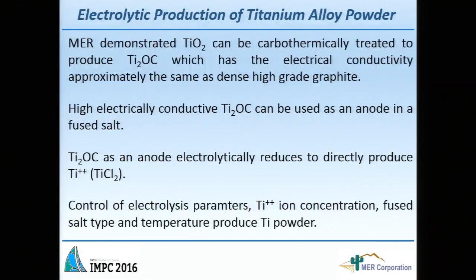And you can make an anode very similar to the cathode that the FFC process made. You make pellets, and you can use this as an anode to produce Ti2+ at the anode side, which then can be reduced at the cathode. So with this step, really, this is an enabling step to be able to produce titanium electrolytically, is to make the Ti2OC.